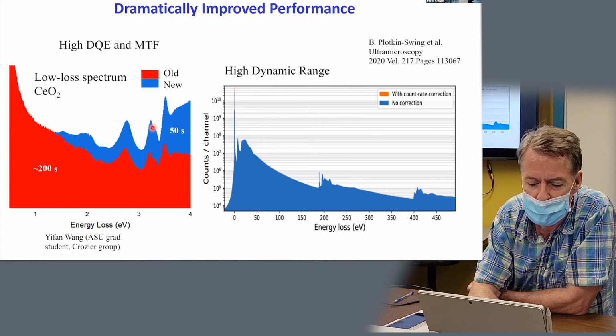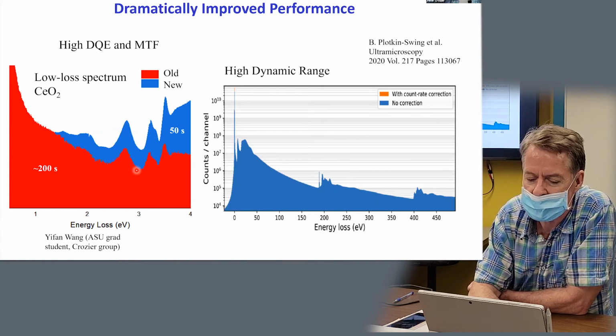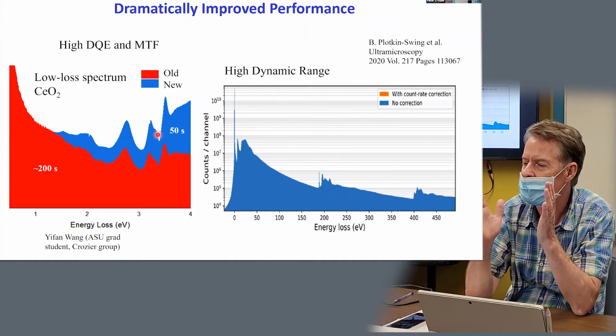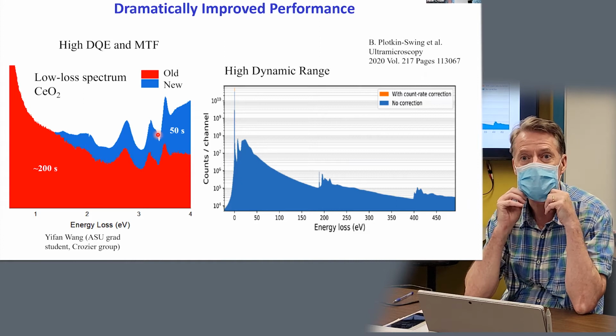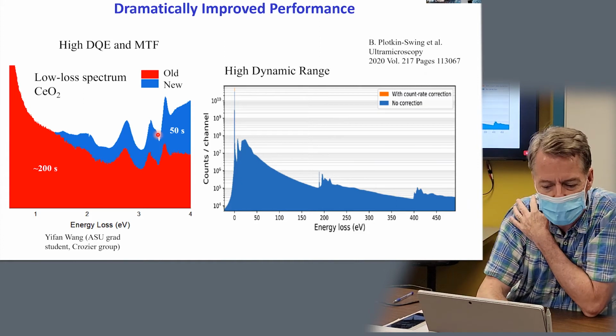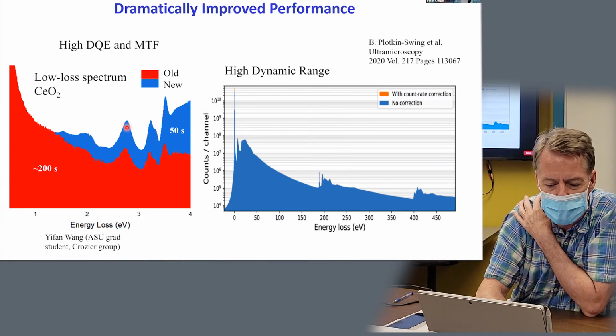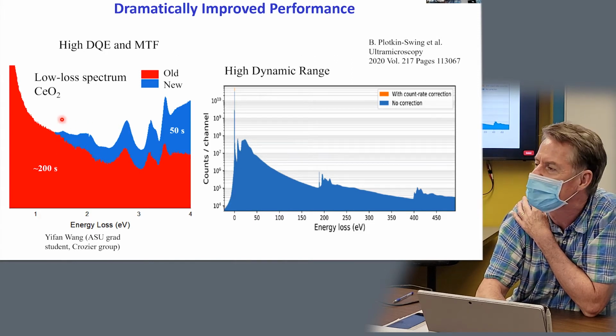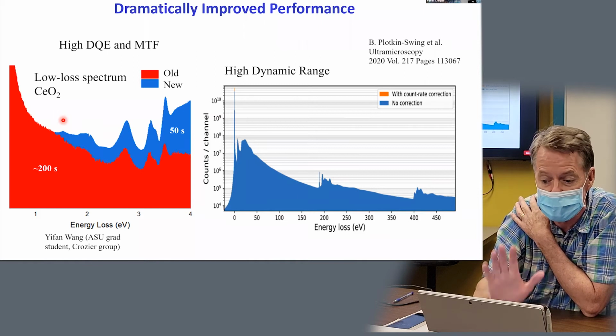But the other thing I want you to notice is that the peaks are much sharper than the red curve. It's exactly the same area of the sample. The peaks are much sharper. That's because the point spread function of this detector is much better. So you get much better quality spectra. And you might say, well, here it doesn't make much difference. But if you look at this part of the spectrum, we're really starting to see things now that we couldn't see before, right? So this is what's great.